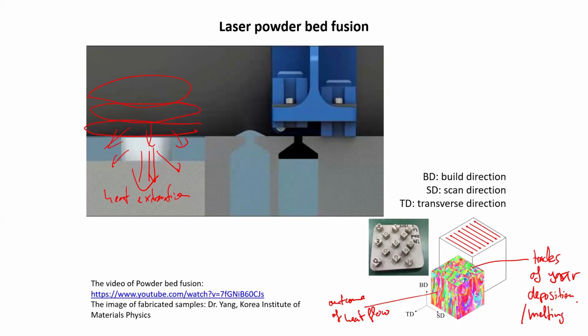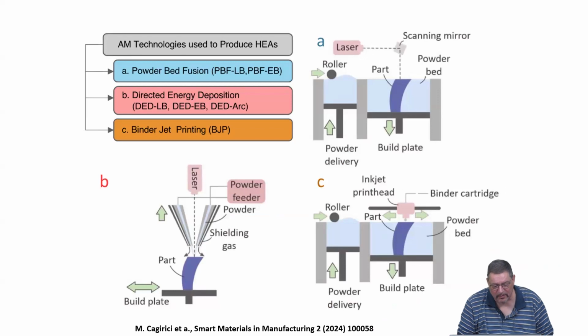So it means that when you want to use it, you probably have to do some post-processing, which is against the idea of additive manufacturing, because you would like to take the part and put it into your device, but this is probably not going to happen. This is not only true for the high entropy systems, but also for others. Yeah, and again, there are different ways of either directed energy deposition, so you don't have a powder bed, or powder bed parts. And in principle, they all have the same benefits of making materials without having to machine them in a strong way afterwards, but all of them also suffer from creating non-equilibrium structures.